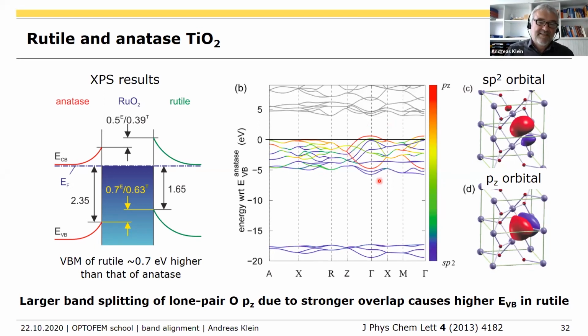So these are the energy bands projected onto the contributions of sp2 and pz orbitals. This was done by Paul Erhart at Chalmers using some Wannier function analysis. And then you see that it's exactly the pz orbital which shows, for a non-bonding orbital, an extremely high splitting. This is the reason why in rutile the valence band maximum is higher than in anatase. The valence band maximum of anatase is the black line here. So with this common anion rule, one has to be careful when you go from one polytype to another. That can really make a difference.